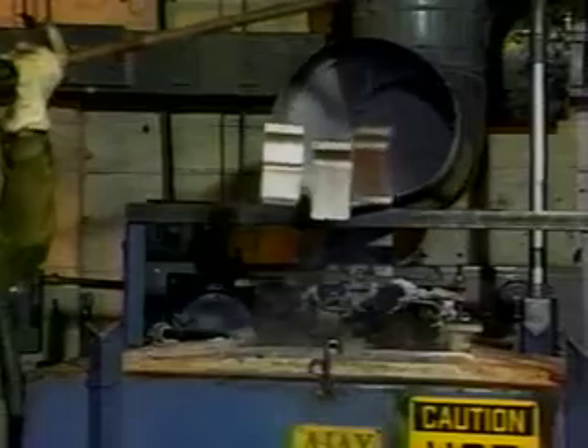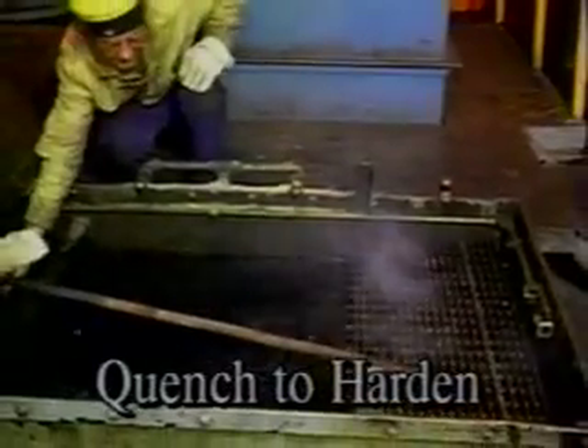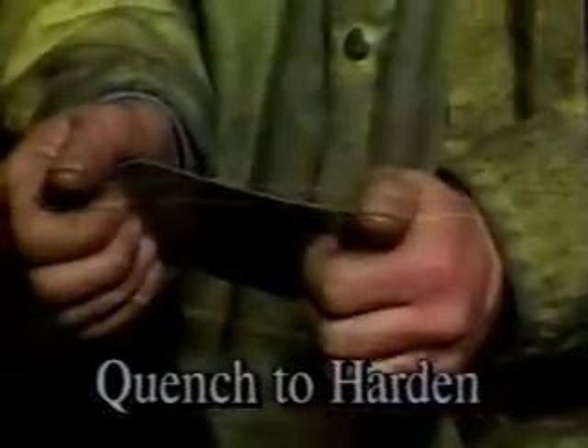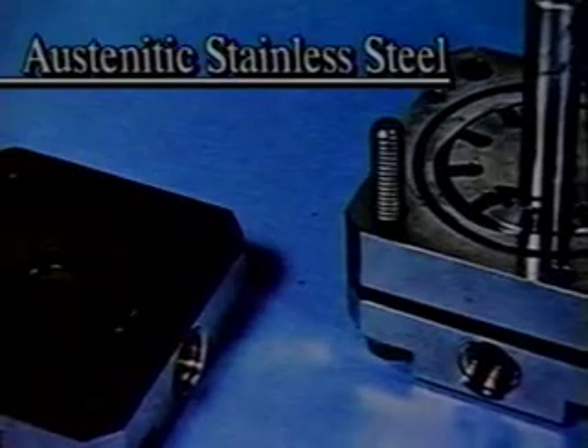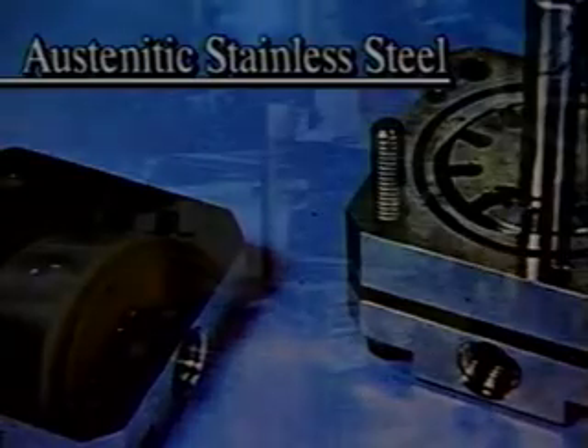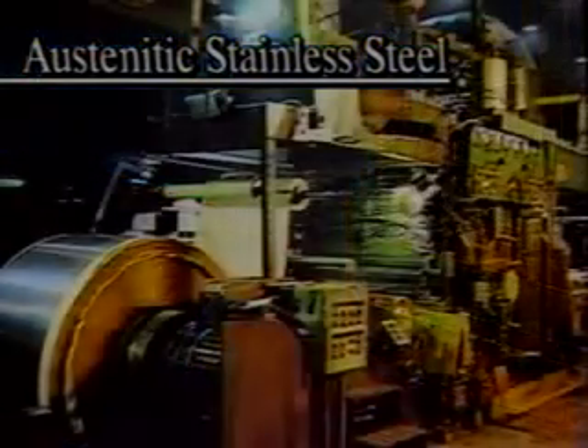Hardening is the main purpose of quenching in the case of a large group of steels, which include plain carbon steels, low and high alloy steels, and tool steels. When these steels are heated to high temperatures and quenched, a hard and brittle phase is formed. This is called martensite. A special class of steels called austenitic stainless steels responds quite differently to quenching.